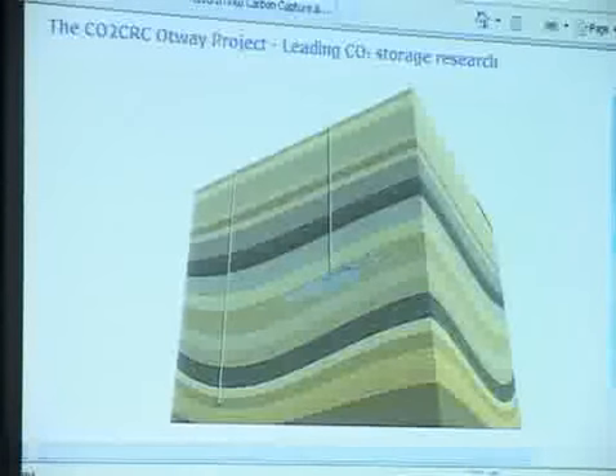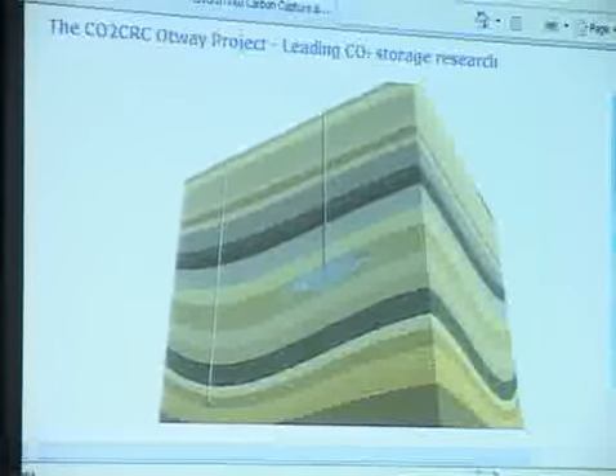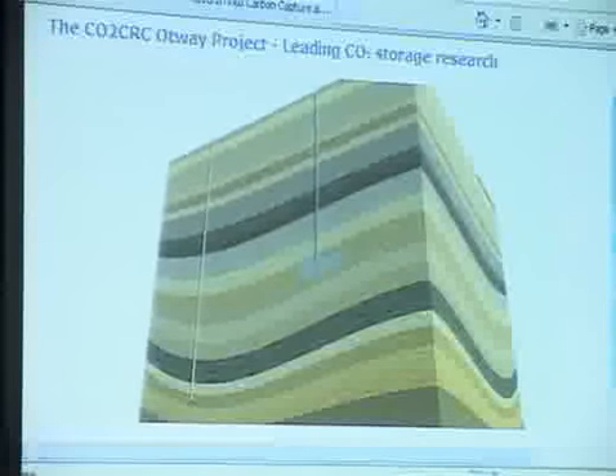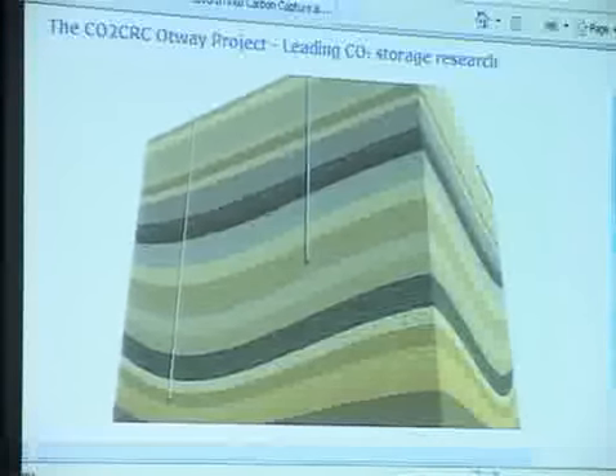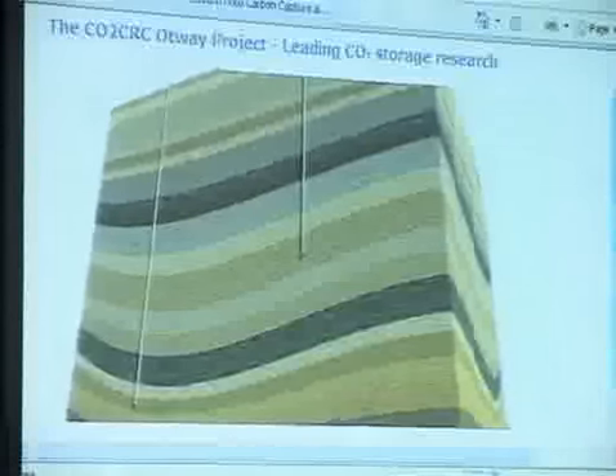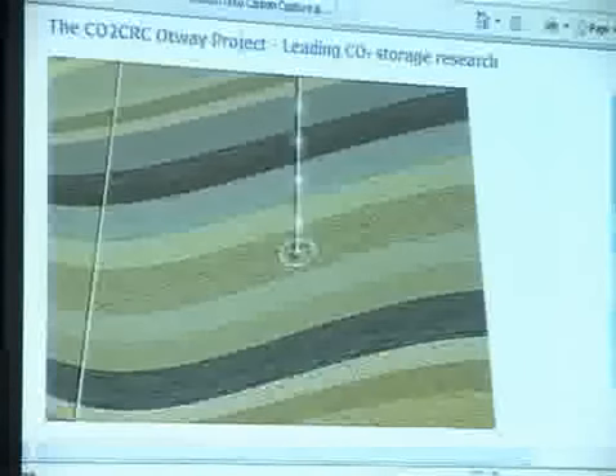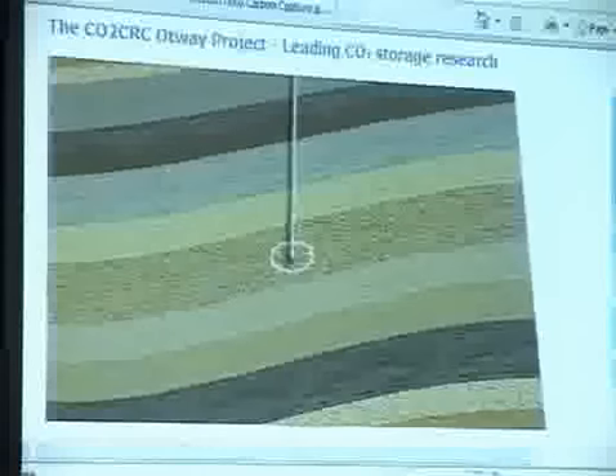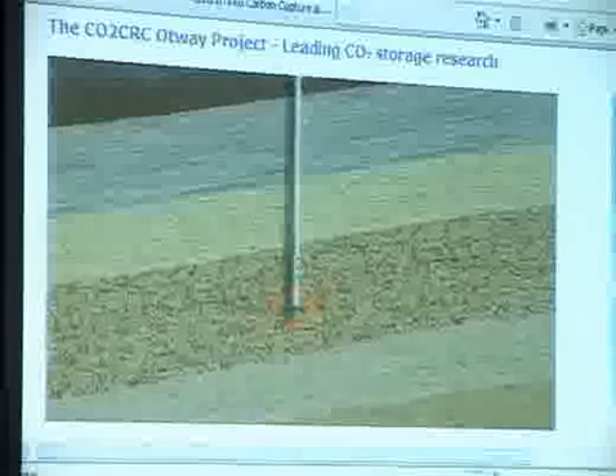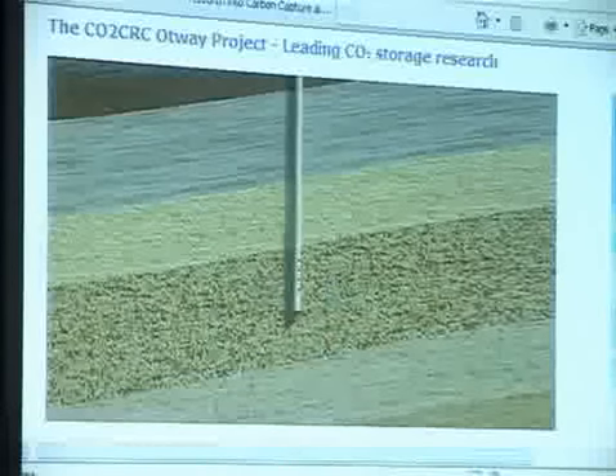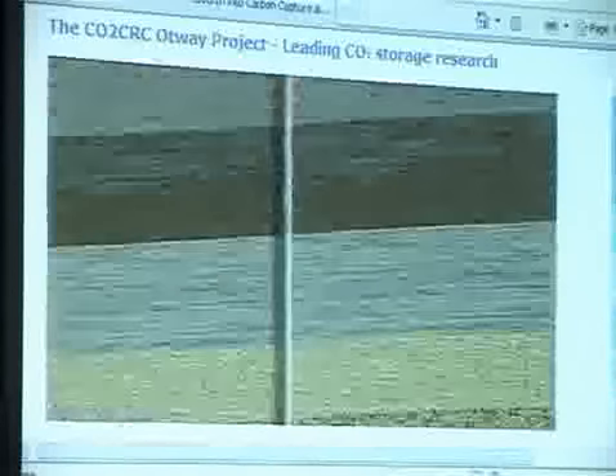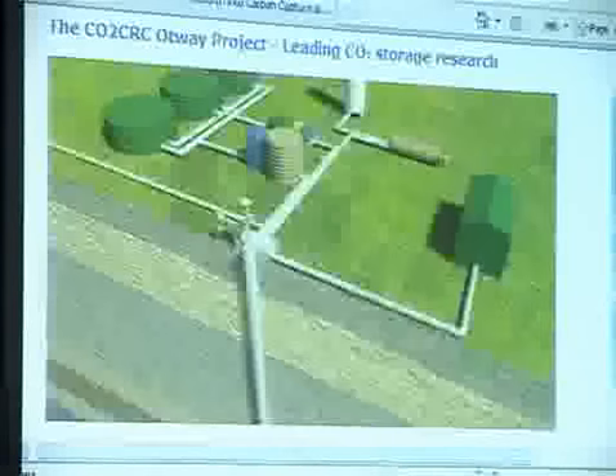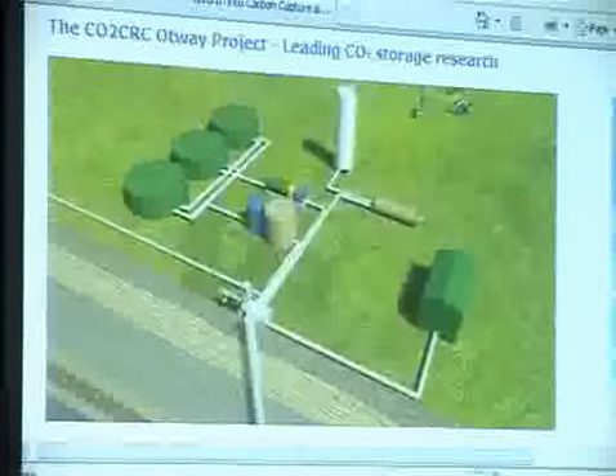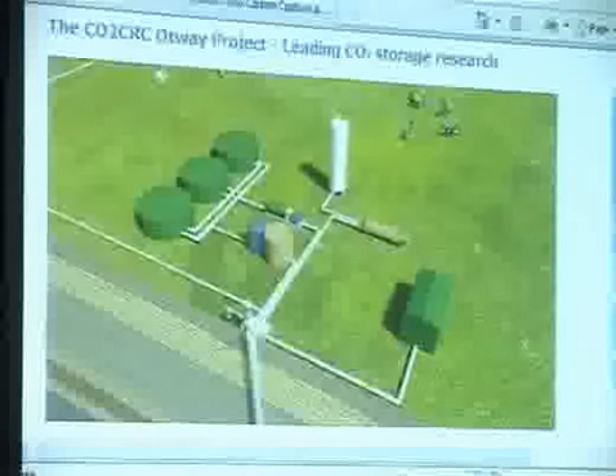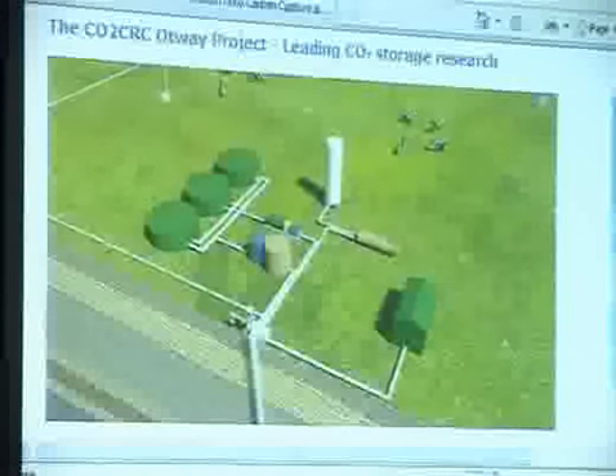Several approaches were used to evaluate how much CO2 had been permanently trapped. Measuring the CO2 content of water extracted from the well showed how much CO2 was left behind. Pressure was continually measured by very accurate downhole and surface gauges throughout the experiment. The detailed temperature profile was measured. Samples of water and gas were taken from the well using the U-tube sampling system and then analysed for tracer gases and CO2. By using all these methods, researchers could compare different approaches to determining the size of residual trapping.